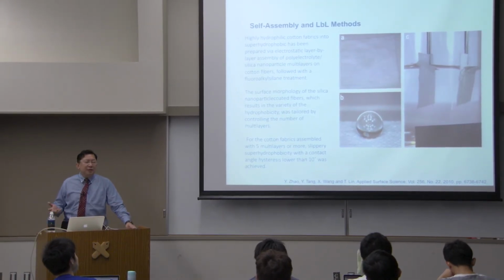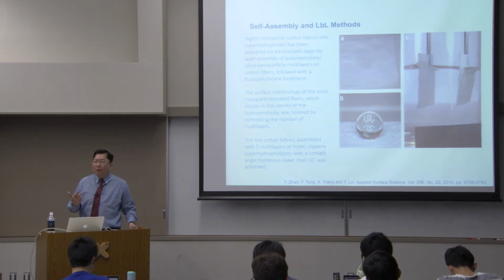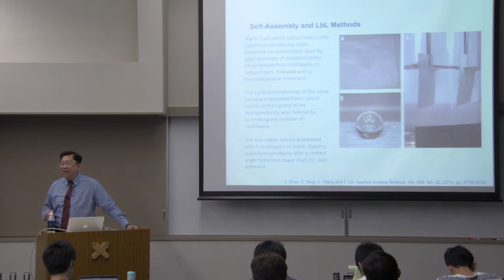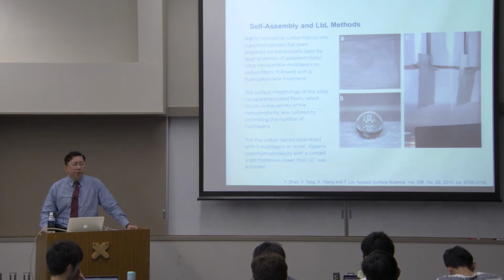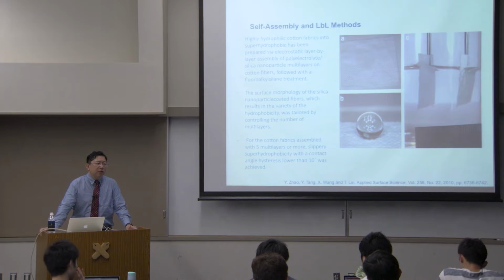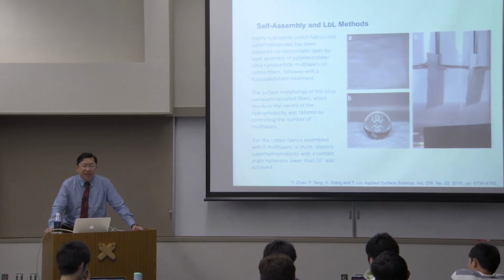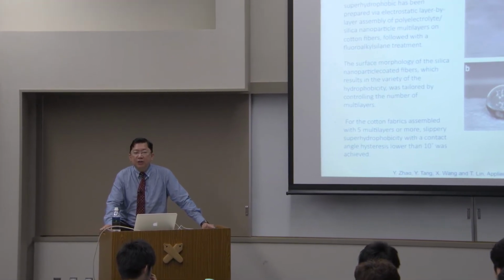So in these past examples, you can see several things. One is that by employing methods that result in a hierarchy of roughness, you can take advantage of the Cassie-Baxter approach. Usually the last treatment, which in many cases is actually not needed, is employing a low surface energy surfactant or amphiphile modifier to further increase the non-wetting behavior. That is a Young's equation approach. So the combination of the Cassie-Baxter and the surface energy approach allows you to make these surfaces from all these methods we've covered so far.